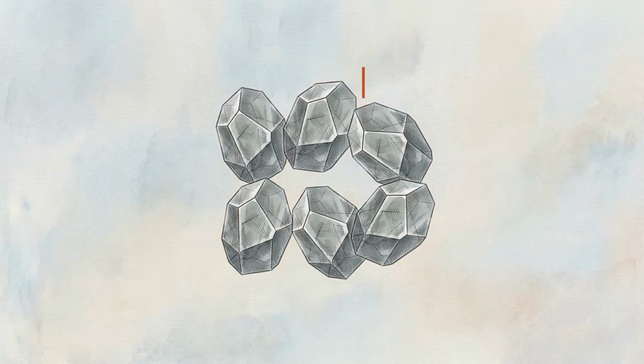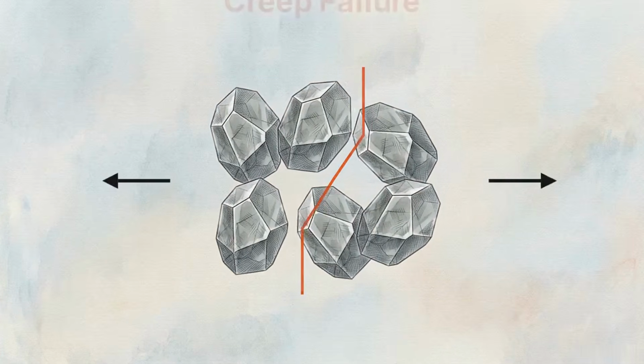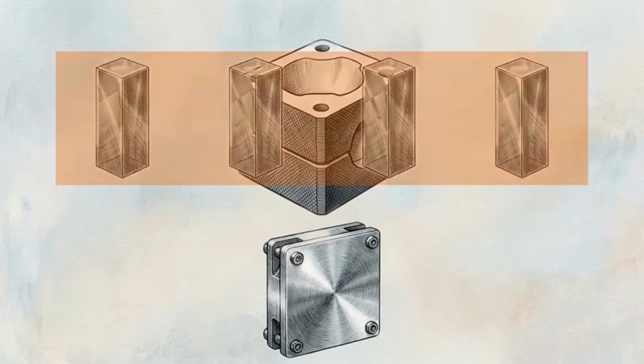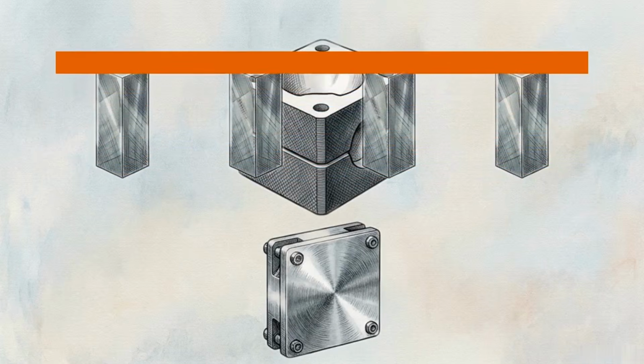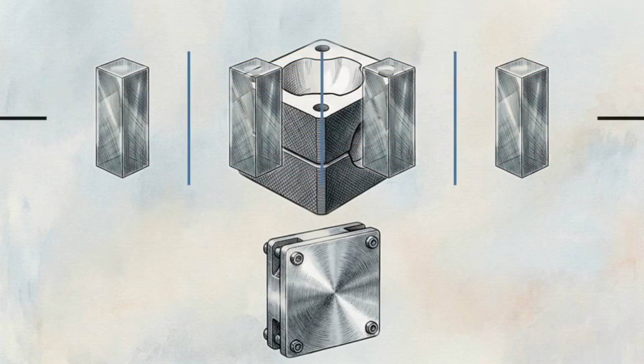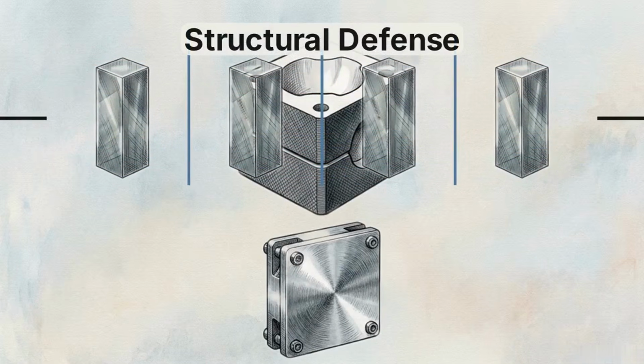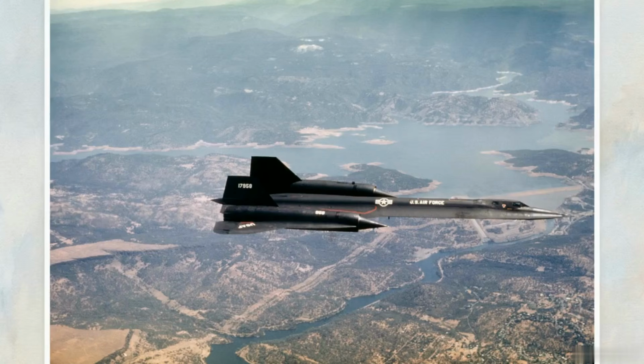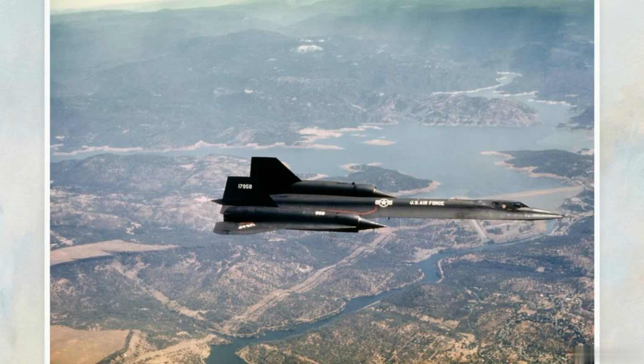Liquid metal cools into randomly oriented crystals. The jagged spaces between them, called grain boundaries, tear apart under stress. To fix this, directional solidification uses a bottom chill plate to freeze the metal upwards, growing vertical columns that eliminate the weak seams. This directional solidification provided the precise structural strength required to build the engines for the SR-71 Blackbird.